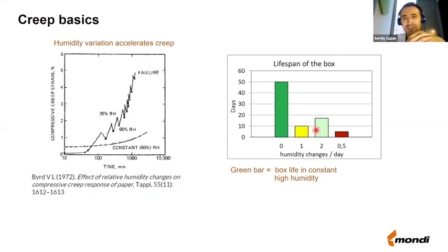And the answer to this question is that it takes some time for the humidity to penetrate through the paper, through the box, and for the box to reach equilibrium. So if the humidity is changing too fast, like in this case where you had 2 cycles of humidity changes per day, the boxes do not get enough time to reach equilibrium. Therefore, the effect of changing humidity is not as strong as where you have a slower change in humidity, because there the boxes really can reach equilibrium, and by cycling this humidity, the boxes are collapsing much faster.